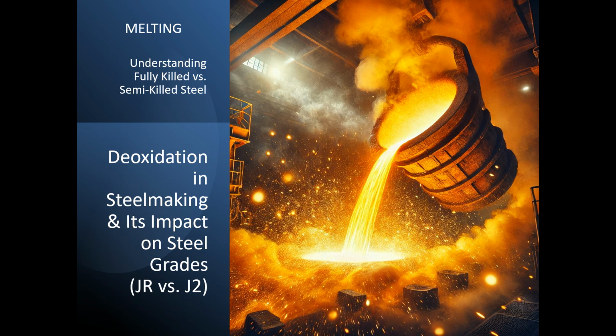Deoxidation is a process whereby the oxygen is removed from the molten steel to prevent oxide formation. So if you can imagine this big melt pot where they put a bunch of electrodes in to arc the ore and get it to melt, and you consume an enormous amount of electricity, this process happens under air. So it's very easy for oxygen to be drawn into the steel.